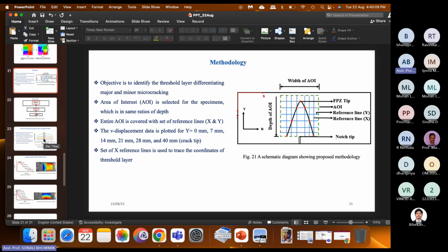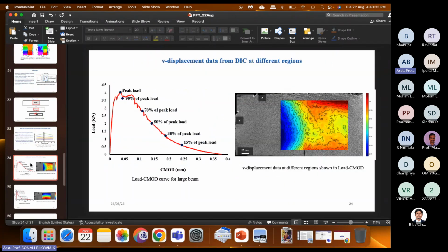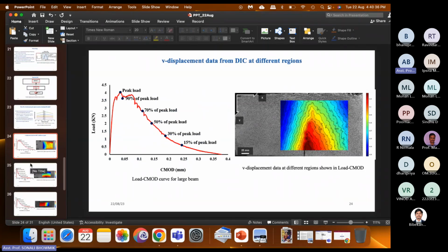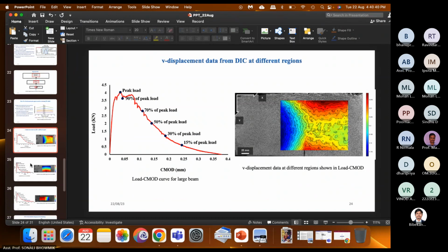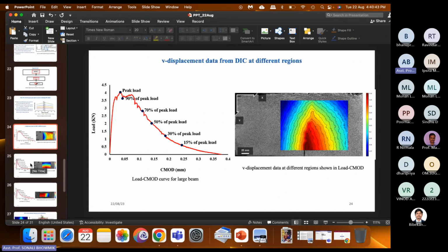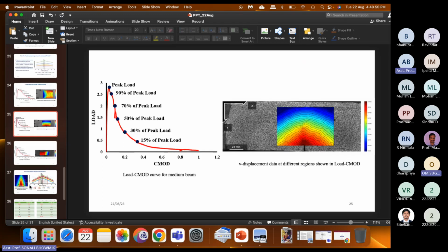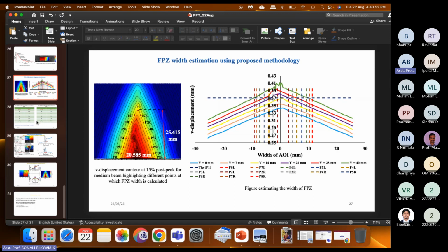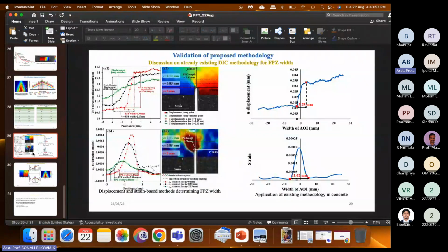Previously it was understood that there is no significance in finding out the fracture process zone width, but eventually many other researchers also found out that it has a significant size, and it is very important to find out. So in this scenario, a set of data was again analyzed, and these are some plots for DIC analysis. If you can see here, this is for displacement data extracted in the V direction. As I mentioned, deformation in the V direction, that is vertical.